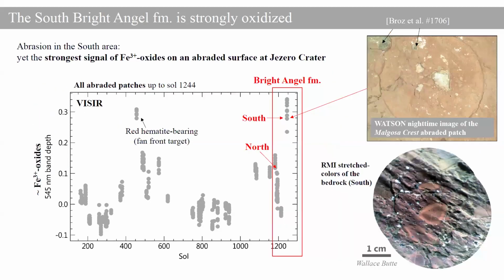So now coming back to this signature of ferric oxide in the visible range, in the next slide, we can have a look at a parameter that quantifies the strength of this signature. And what we see in this plot is the evolution of this parameter for abrasion measurements over the course of the mission. And what we see is that the abrasion in the south area has yet the strongest signal of ferric oxide on an abraded surface at Jezero so far. And that is what is giving its red color to the southern bedrock, which is strongly oxidized. You can see on the left that the last time we saw a similar signal was at the front of the deltaic fan on a target with hematites.